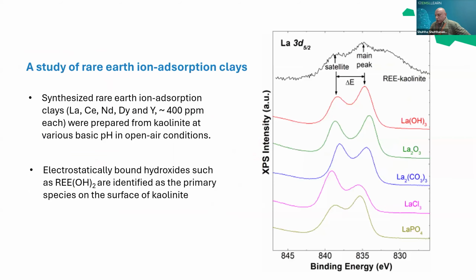Okay, so let's go to the next slide. We also did a similar study in the kaolinite. This is the lanthanum deposited on kaolinite, around 400 parts per million lanthanum. Here they did some different lanthanum compounds' XPS, and then they compared with the actual data, and they found out that in this particular adsorption, the lanthanum is bound to the hydroxide surface. It looks similar to the hydroxide XPS peak.